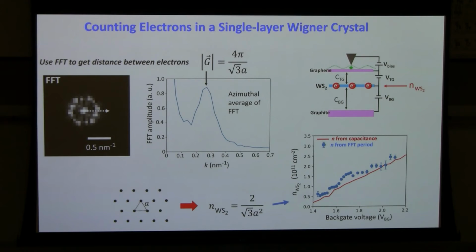And something else that we can notice is that this is where we believe we're seeing the melting. In this regime that I highlight in green, that's where we stop seeing the lattice. It disappears. But if you look at the prediction from the theory, this gamma equals 34 prediction, they predict that the melting should occur at this lower density. So according to our data, it looks like we're seeing the crystal living to higher density than is theoretically predicted.